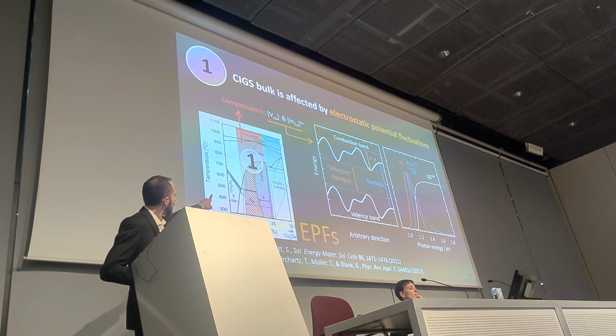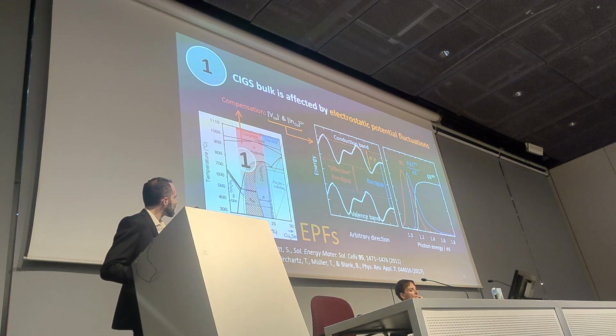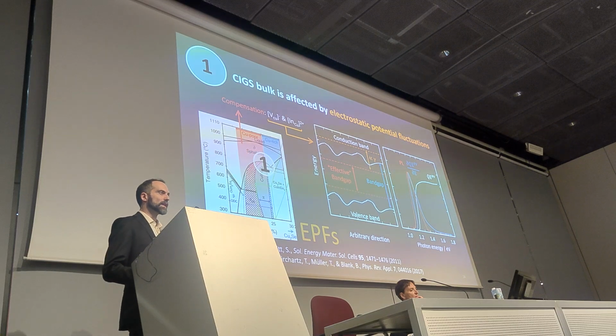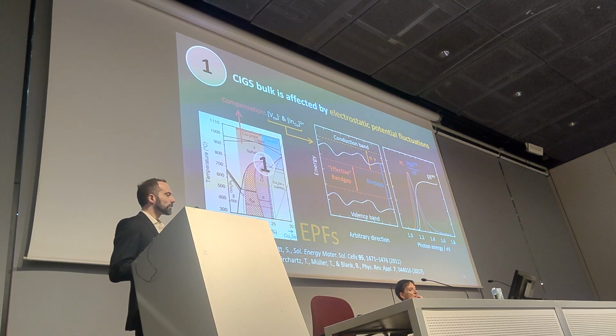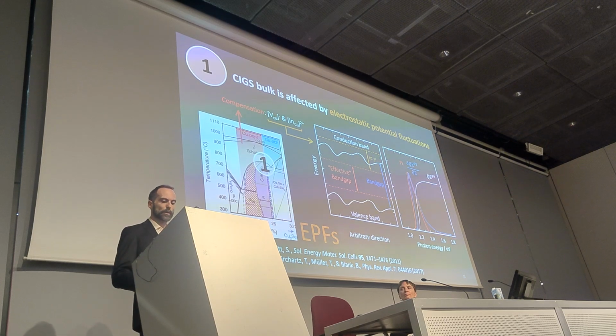And now, I'm going to move this one dot towards the copper poor and see what happens there. The extent of fluctuations increases because we are increasing compensation. So the more poor we get, the more this compensation is detrimental for the device performance. The more we go to the copper-rich configuration, the better would ideally be the performance of the device.